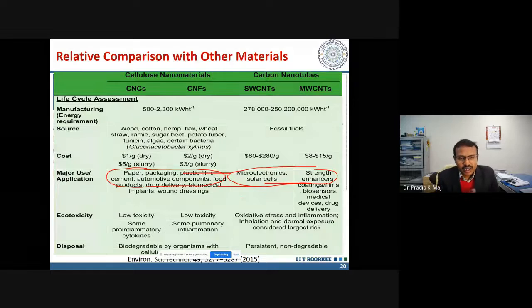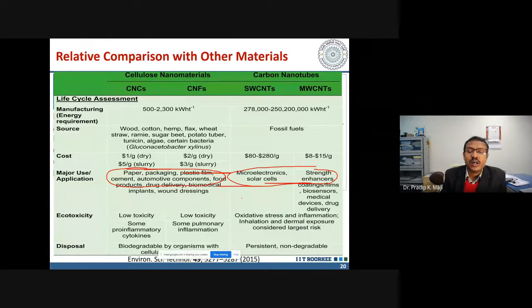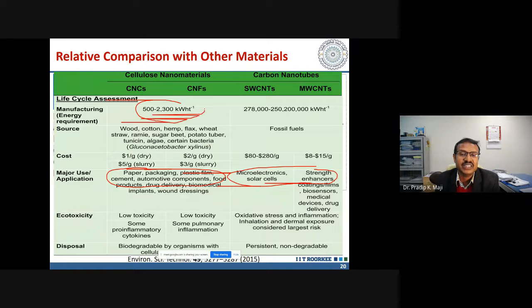But if I go to the other aspect - manufacturing cost - try to compare the manufacturing cost. Carbon nanotube, whether multi-wall or single-wall, the manufacturing energy requirement is very huge, around 278,000 to 250,000,000 kilowatt hour, whereas the energy requirement for manufacturing cellulose nanofiber is very, very less. That means making cellulose nanofiber is energetically feasible.